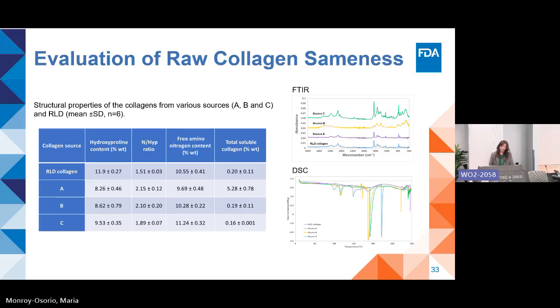Regarding the structural property characterization results, the collagens we investigated show comparable hydroxyproline content, nitrogen over hydroxyproline ratio, and free amino nitrogen content. Similarly, we found that the FTIR characteristic peak patterns behave similarly among these collagens, including RLD, regardless of the variation in the sources. However, differences were observed in the solubility of the collagens, where collagen A shows higher solubility compared to collagen B, C, and RLD. And regarding the DSC analysis for thermal stability, we found that collagen A shows weaker thermal stability compared to the moderate thermal stability of collagen B, while collagen C and RLD show stronger thermal stability.